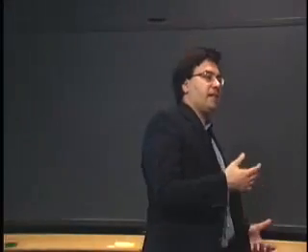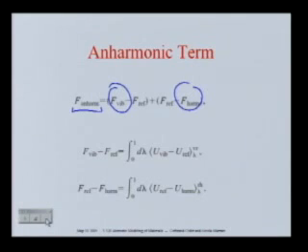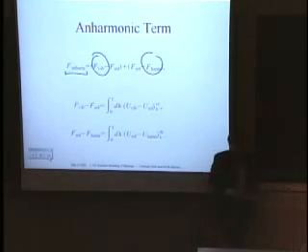So by introducing basically a reference potential, you are shifting a lot of the thermodynamical integration to the classical simulation, and you're just using the quantum mechanical simulations to sample the difference. And so this can be done actually with much shorter and much smaller simulations.